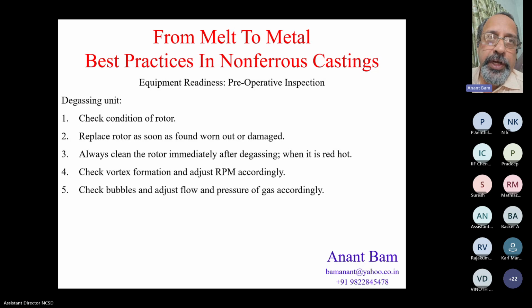Because the oxide which is deposited on the rotor along with the aluminum metal is in a soft, porous condition till the time it is red hot. You can remove that by scraping with any hand tool like a long blade or a long strip, and it will keep the rotor clean. If it is not cleaned when it is red hot, then after cooling, the oxide becomes corundum, and that's a very hard material. You cannot remove that. If you try to remove that, the rotor will break. Next slide, please.